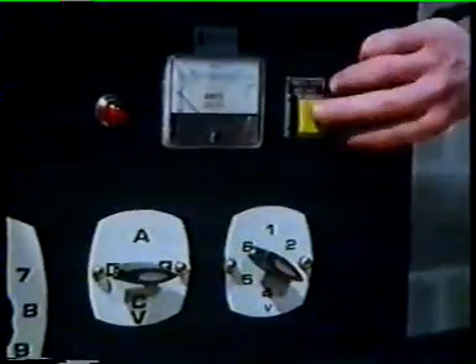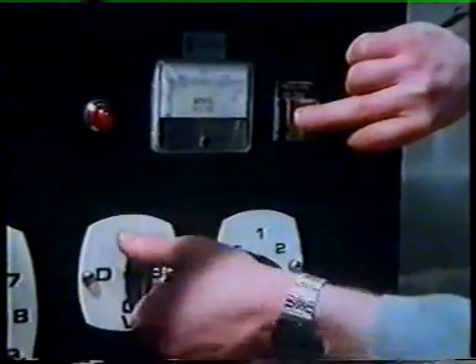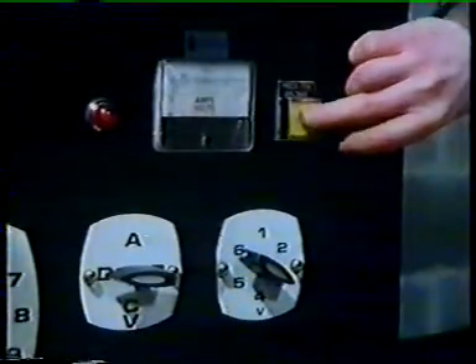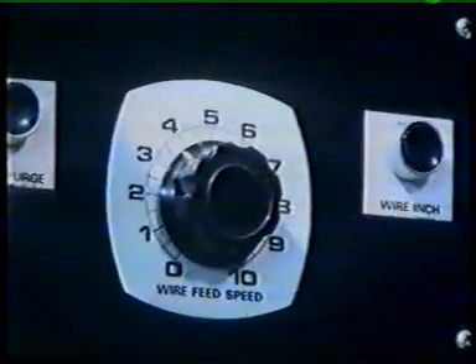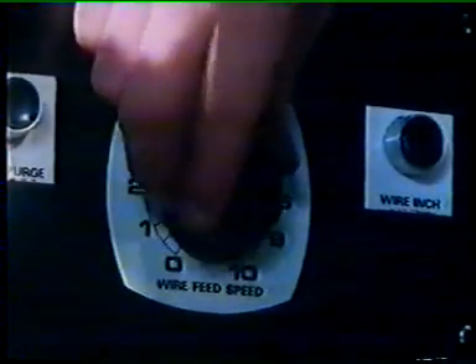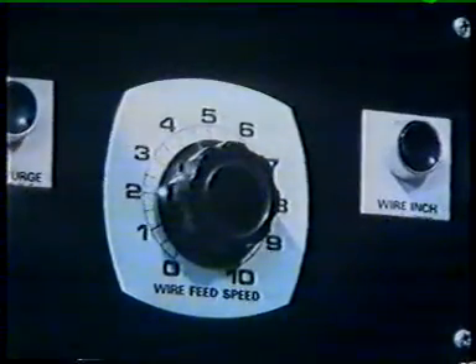The weld is of similar quality to the weld you get with manual metal arc, but there are advantages. There's no need for frequent electrode changes, and there's no flux to be removed. If you increase the current beyond 300 amps, MIG can be used for thicker plates and aluminium. The speed of the electrode feed has to be increased to deal with the higher current, and this gives a very stable arc and uniform melting of the electrode. The process is called spray transfer.